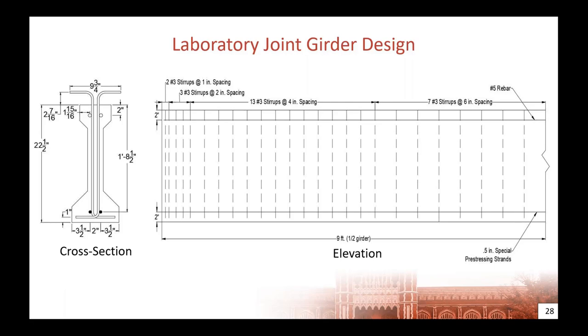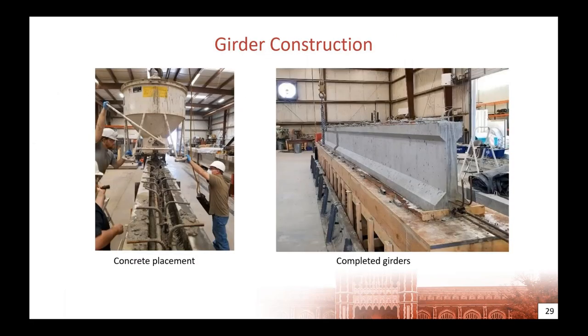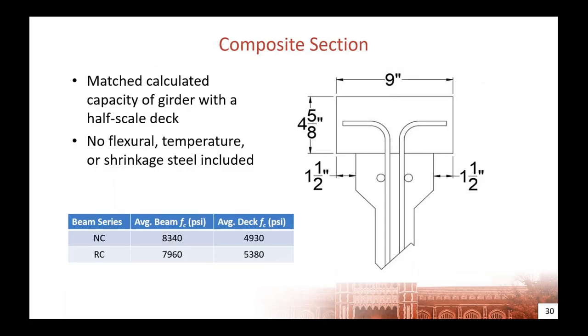But in the lab, we started by looking at about half scale joints using an approximately half scale AASHTO girder that had two pre-stressing strands in the bottom, number three shear stirrups that extended out of the top of the beam to create a composite section. And these beams were about 18 feet long. The beams were constructed in our lab at the University of Oklahoma, including the pre-stressing as well as the concrete casting. And once we cast the beams, we created a composite deck with those beams that was intended to match a half scale bridge section. So it was a narrower section with a slightly larger thickness to give us the same moment capacity. And we had concrete in the beams of about 8,000 PSI and the decks were about 5,000 PSI.